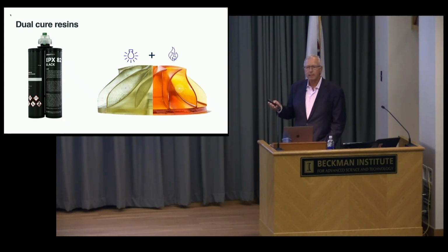So we have a resin that we keep photochemically curable and shapeable. But a lot of the best polymers are made by reactive liquids. Think about epoxies and polyurethanes, polyureas, silicones, cyanate esters, you name it. Mixing liquids come together, highly reactive systems. No one in 3D printing went down that direction because the printers were too slow and the resins would prematurely polymerize. But because we're going 100 to 1,000 times faster, we knew we had a window of operability.